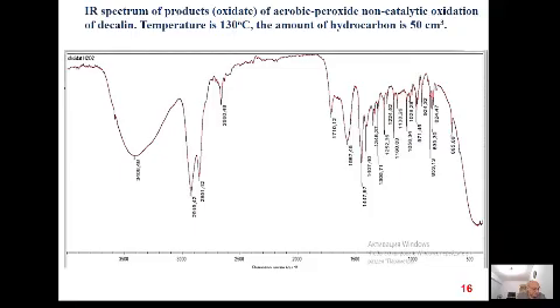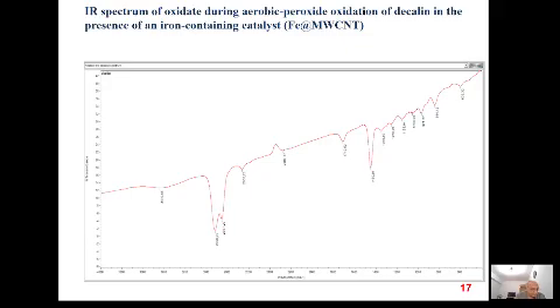The next slide shows the infrared spectra of products of aerobic peroxide oxidation, non-catalytic and catalytic oxidation of decalin at 130 degrees. For the oxidate, the absorption bands of the symmetric, asymmetric, valence and deformation vibrations of the oxygen-containing group bonds are clearly seen from the spectra. Characteristic absorption bands of the aromatic rings at the region near 1,400 reciprocal centimeters and valence vibration of the CH bond of alkanes and cycloalkanes in the region of 2,900 reciprocal centimeters are also observed.